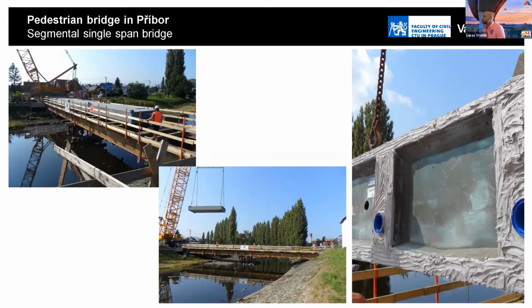So it was interesting but very important to produce the closing of the joint, and also to satisfy the conditions for the glue. And also it is important to satisfy the condition for the closing of the couplers, because it is important to put them together. The connection is not done only by the surfaces being close together. You have to move some elements through another one. So this effect with the bars was very good also for this way of construction of the prestressing.